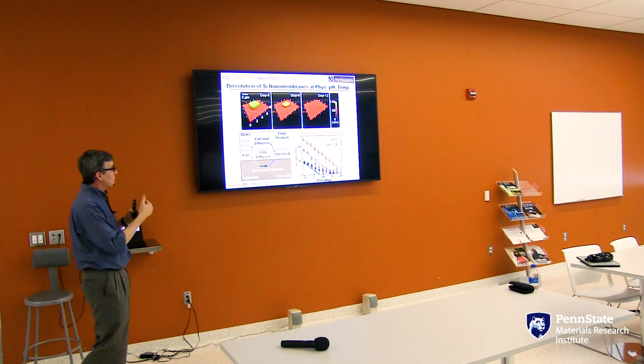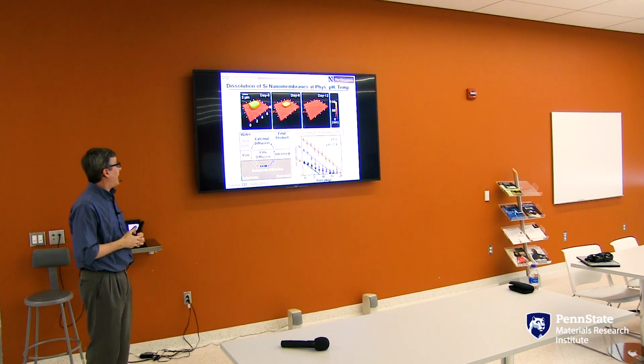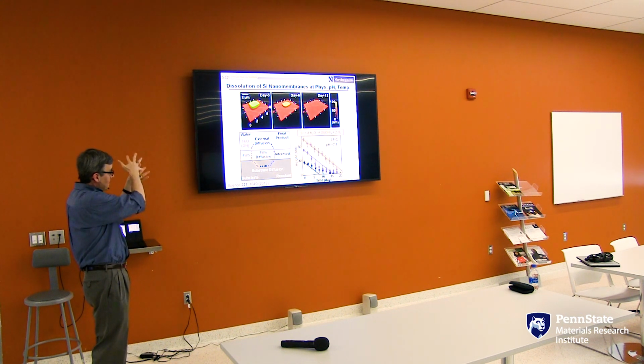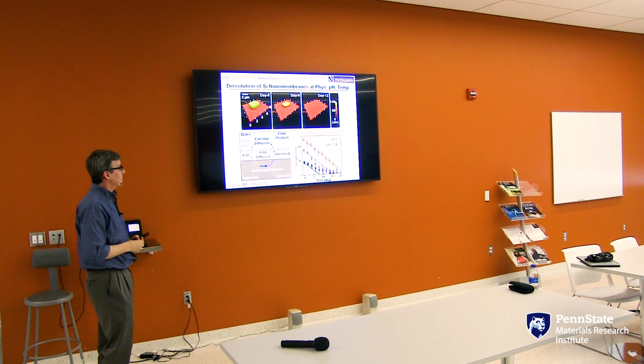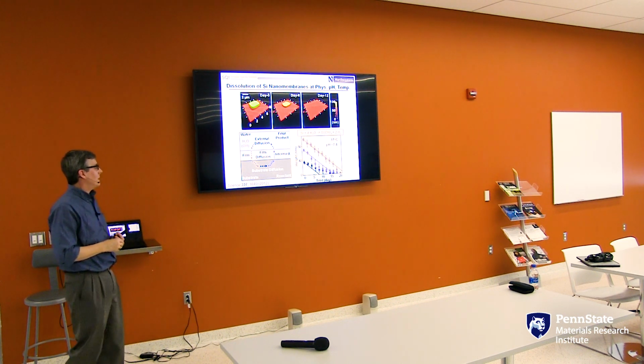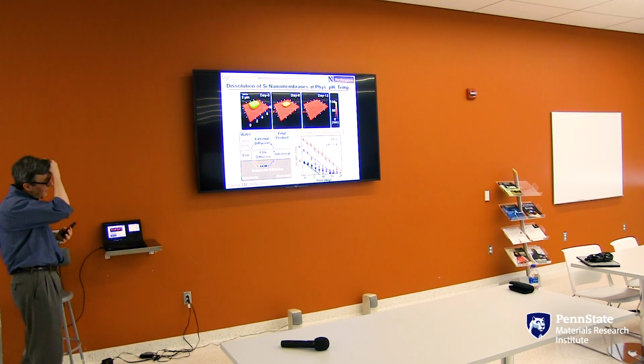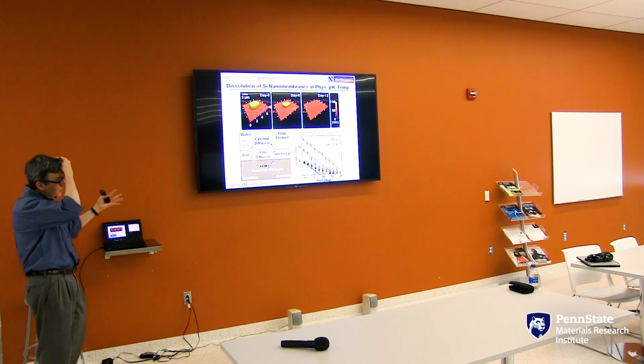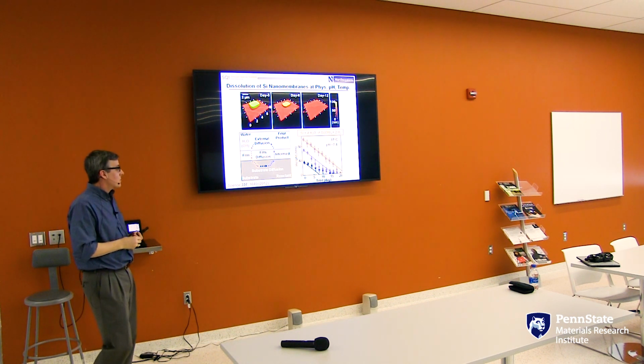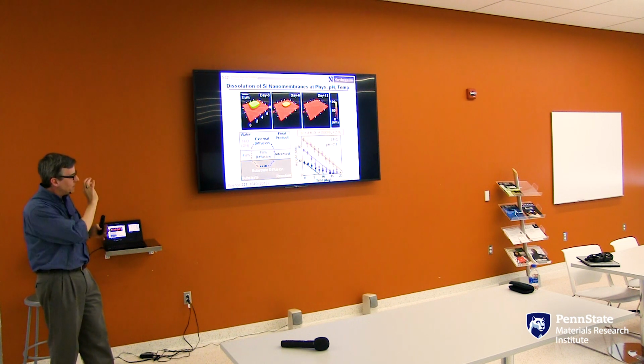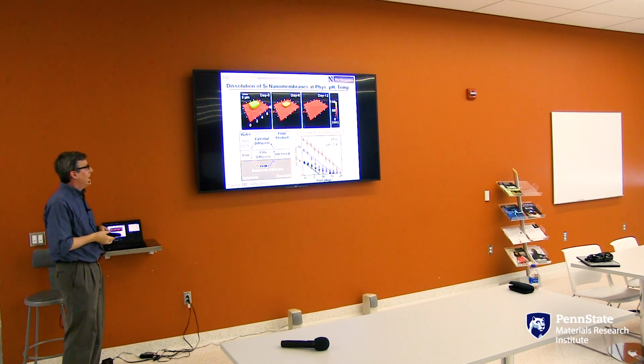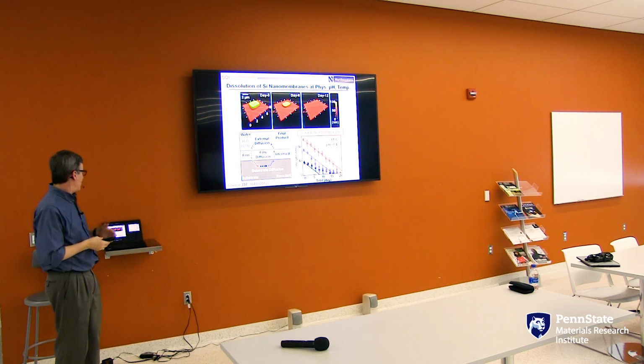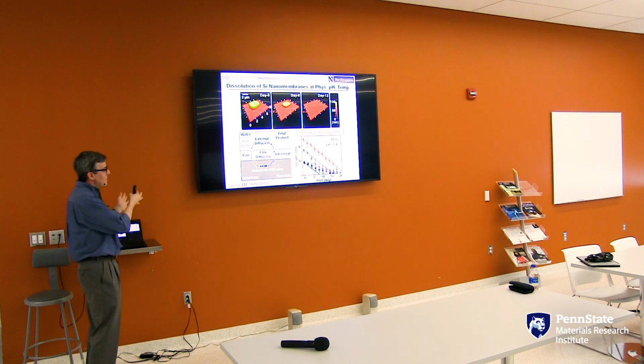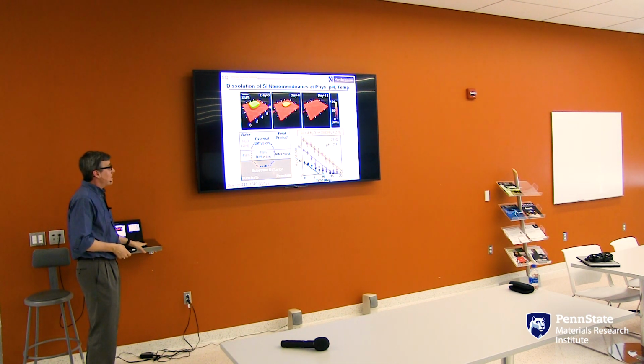And it's happening via surface erosion. And you can just track it. And so you can just track the thickness of these pieces of silicon as a function of time of immersion in an environment like that, and it will dissolve completely. For 100 nanometer thickness, it's completely gone in about 3 weeks. So you have to be watching for it, but it definitely occurs. And that was an observation that allowed us to really move very rapidly into this area of bioresorbable electronics, with silicon as the foundational semiconductor material.